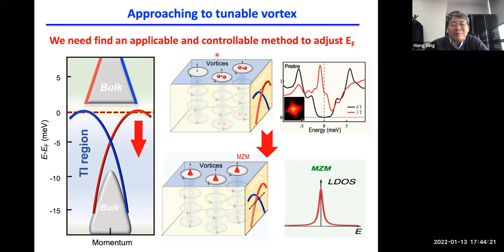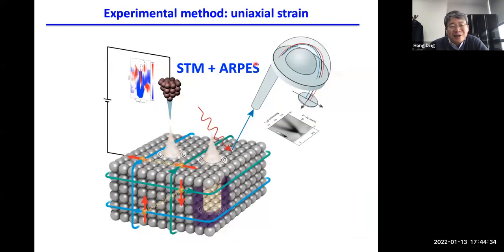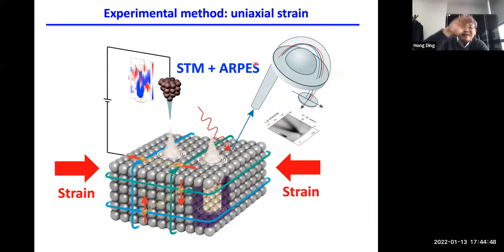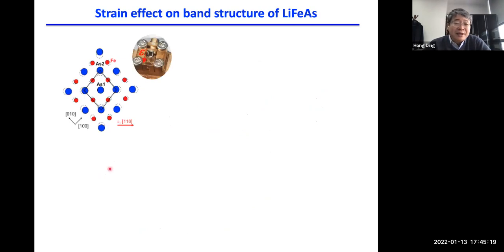But we do need a controllable method to adjust the E_F, not like the impurity. Impurity is non-controllable. You don't know how much doping it will add. So we found a way, uniaxial strain, and it turned out to be a great way to do this. Because in the iron-based superconductor, essentially it's a zigzag structure. So iron ions and arsenic ions stay not in a plane, but in a kind of zigzag fashion. So it's like a spring. When you press with uniaxial strain, it can change the bonding angle easily. And so we found that it's great. It's actually very simple. We use a simple device with a screw to apply strain.